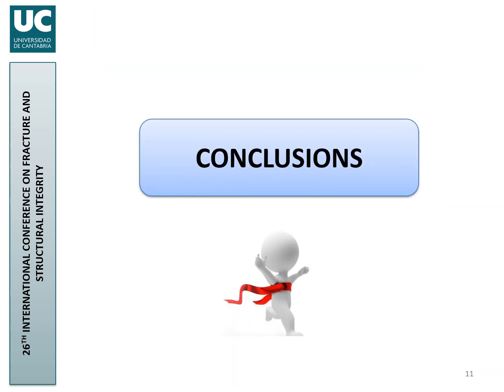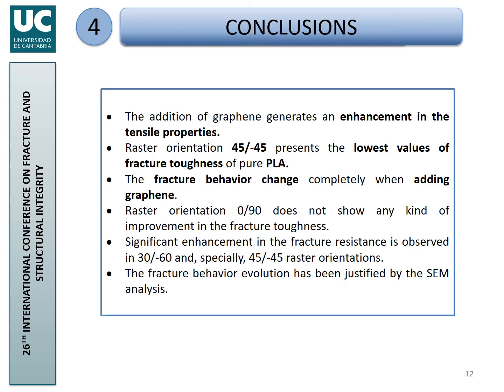The main conclusions are: the addition of graphene generates an enhancement in the tensile properties, this enhancement being dependent on the raster orientation. For example, we saw that the tensile properties had a larger change in the case of 45/-45 raster orientation.